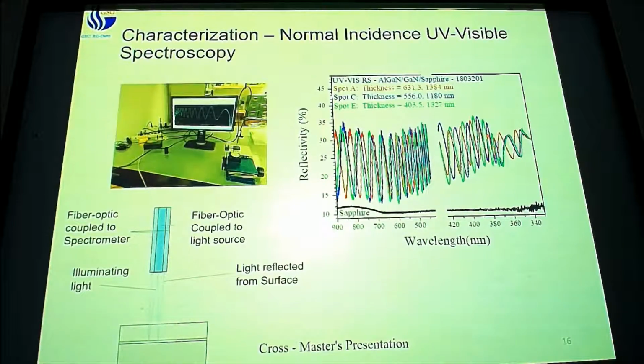So the first thing I want to look at is how thick the material is. So I place it underneath a fiber here. Those fibers connect up to a spectrometer and a light source that's hidden behind the computer. We shine light on this sample here. The light bounces onto the sample, reflects back up, and we collect it in the spectrometer. And we see thickness-dependent fringes.